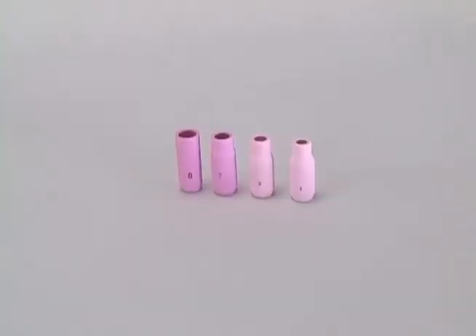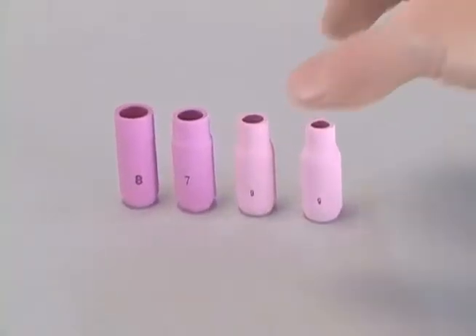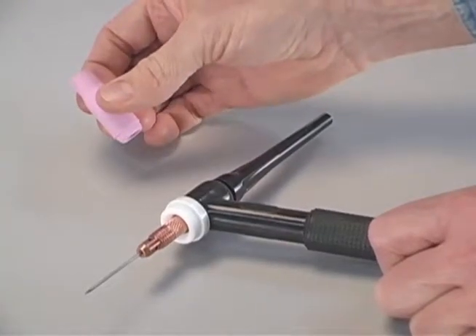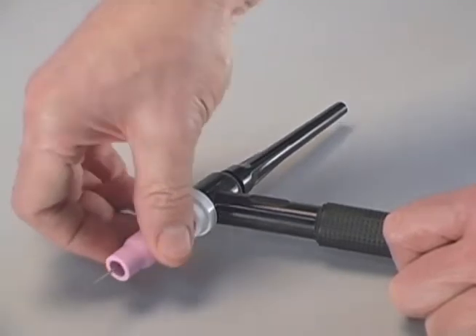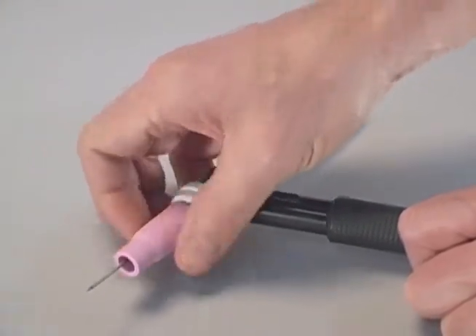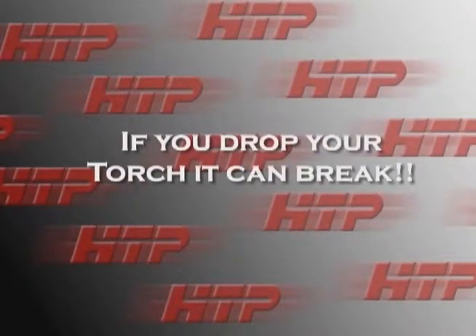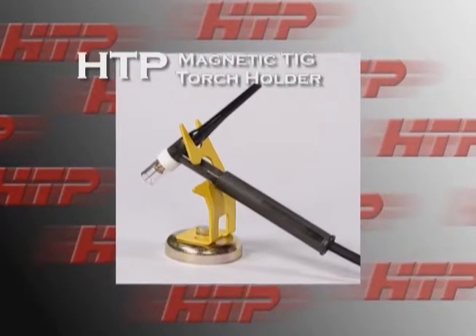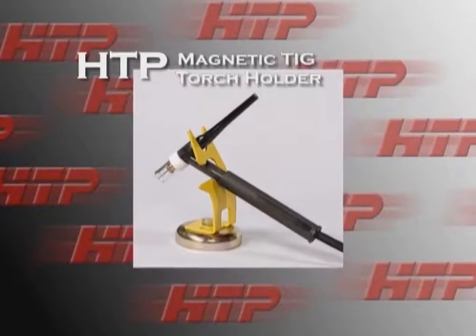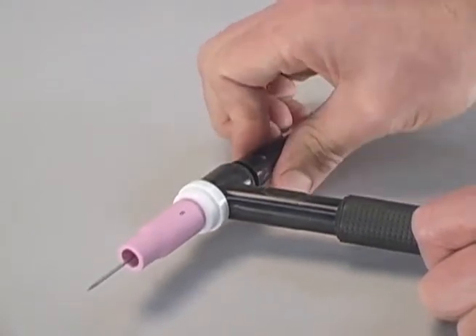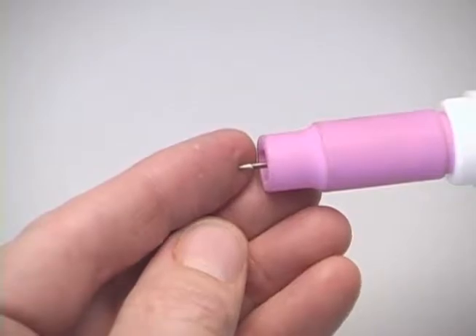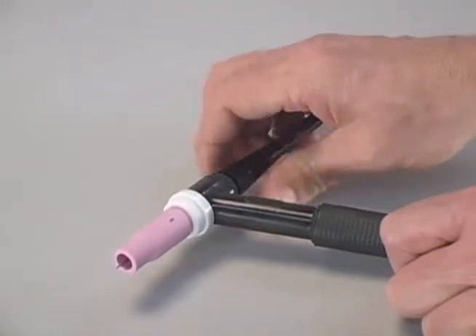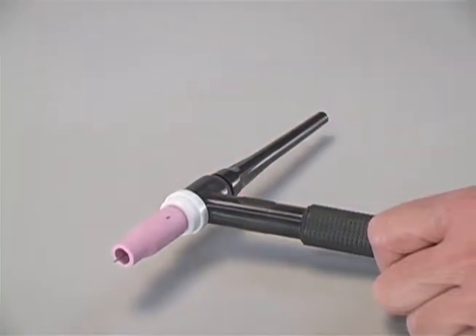Alumina cups have different sized openings, which are numbered and marked on the cup. The number corresponds to the opening size in 1/16 of an inch, so a number 8 cup would have a 1/2 inch opening. Thread the alumina cup on the torch. Remember, if you drop your torch, they can break. That's why the magnetic TIG torch holder is such a nice accessory. It always keeps your torch within arm's reach while preventing it from falling on the floor. If we loosen the back cap, it allows us to adjust or remove the tungsten. Tightening the back cap will force the collet against the collet body, securing the tungsten in the torch.